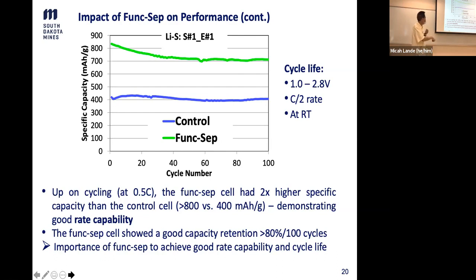And then here it shows the importance of the functional separator for good rate capability. Remember, when we did the plot for the discharge curve, we did it at C over 20. Here we did C over 2. The reason being that A, it is faster, so we get more data. B, C over 2 means 2 hours, which is closer to practical usage. So that's reflected by the rate capability. Just by changing the functional separator, you have those advantages.